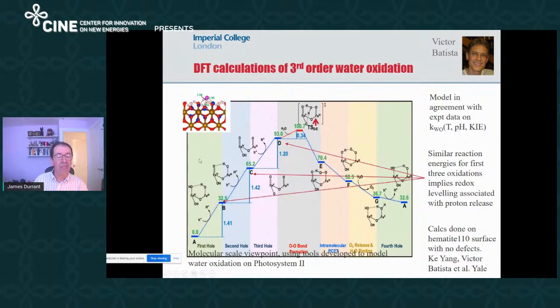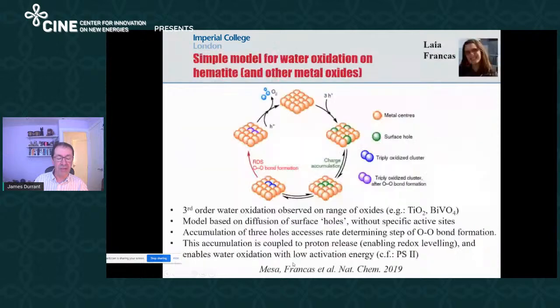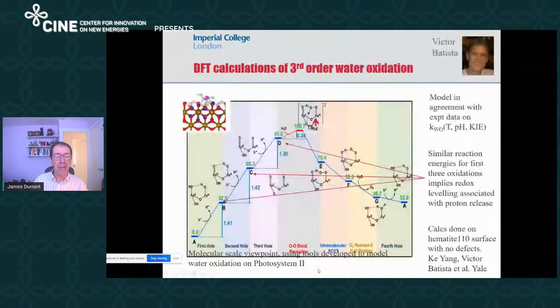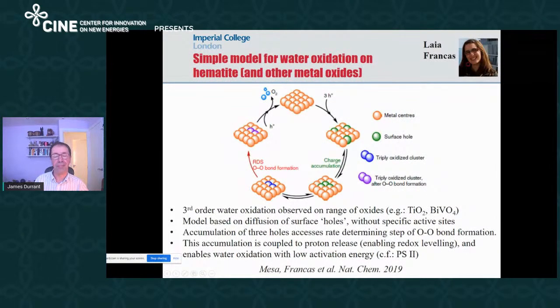And the nice thing here is that the model which he's used, I'm sorry, you can't quite see it, is a molecular scale viewpoint. So the model applied here is the same model used to describe water oxidation in the manganese cluster of PS2. It's different from the models typically used to describe catalysis on metal surfaces. It's a localized model around localized states. And the simple model is the idea that three holes have to come together, and the rate determining step is this oxidation, is OO bond formation, which requires three holes to come together on two metal centers to drive the reaction.